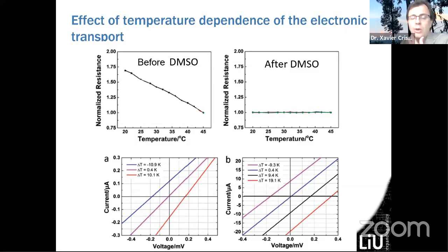So what we have done is change the organization of the polymer using a treatment of DMSO vapor. By doing that, you change the morphology of the polymer and get a very highly conducting polymer. The conductivity increased by three orders of magnitude, and we end up with a material that is almost metallic.